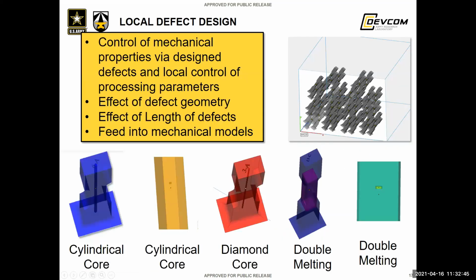And then, bringing in being able to use local processing parameters or induced defects, we're looking at controlling mechanical properties of this material via designed defects and local control of processing parameters. In doing so, we're looking at the effect of defect geometry.